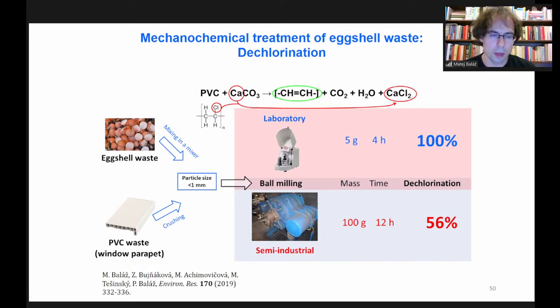We also, as I mentioned, use the process of mechanochemical dehalogenation, and we used it in this investigation. In PVC waste, like a window parapet, we have chlorine, of course, and it cannot be combusted in a regular way because toxic dioxin would be formed. But if we somehow get rid of the chlorine there, the environmental problem is much lower. So in our experiments, we milled it together with eggshell and we observed the formation of calcium chloride. This is a chemical which can be used for drying, for example.